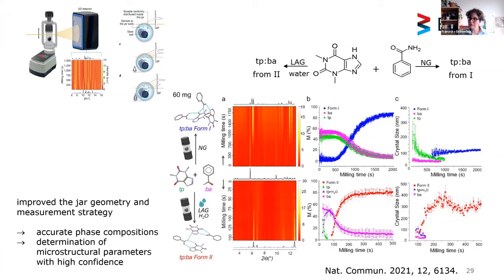And these data compare very well to measurements Ana Belenguer and Aurora Cruz-Cabeza performed a few years ago, where they could show that really the size of the crystallite defines which polymorph is formed in the end.